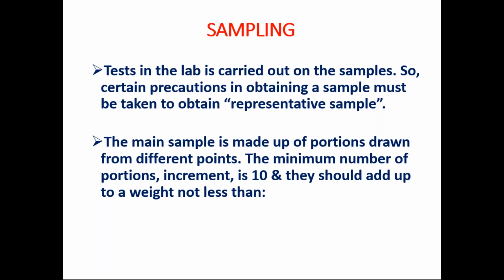Sampling: whenever you want to test the aggregates, first of all, the aggregates shall conform to the various requirements of IS. So when you want to test the aggregate in the laboratory before actually using it, sampling plays a very important role. It should be a representative sample. Many times the aggregates available outside are of very good quality, but the sampling is done in a bad way. Thereby, the result from the laboratory may indicate the aggregate sample doesn't conform to the requirements of IS. That's why the representative sample must be selected properly by taking various portions.